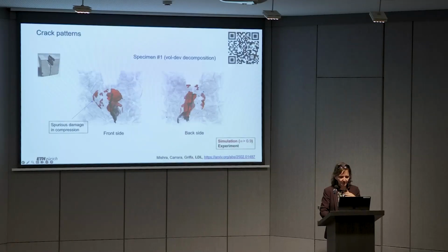But what I want to focus on now, just as a little motivation, is that none of the energy decompositions that are available so far, so this split of the elastic strain energy density into this coupled part and uncoupled part, is really satisfactory. In this setup, we were using the volumetric deviatoric decomposition, and apparently the crack was reproduced pretty reasonably, but then we had a lot of spurious damage. And when we looked more closely, we found out that this spurious damage was due to compression, in fact.